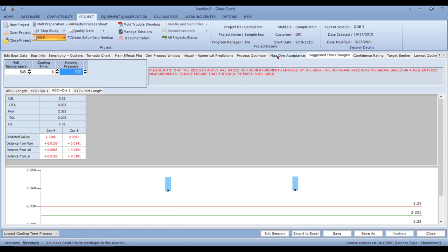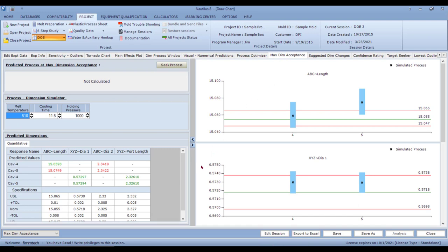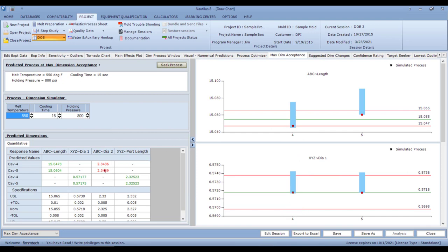The Max Dimensional Acceptance tab finds the molding process where the maximum number of dimensions are acceptable — not necessarily at nominal, just within spec. Click 'Seek Process,' leave out cavity 5, deselect diameter 2 and port length, and click OK. It tells you that 550°F, 15 seconds cooling, and 800 PSI holding pressure puts the selected dimensions within specification. Remember: being in spec is not the same as being capable — that's process capability, Cp and Cpk.